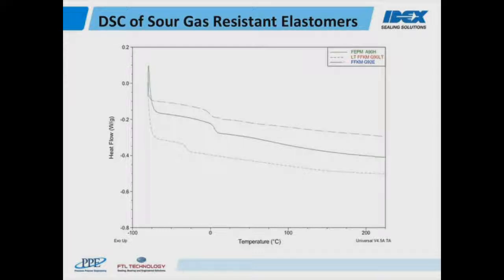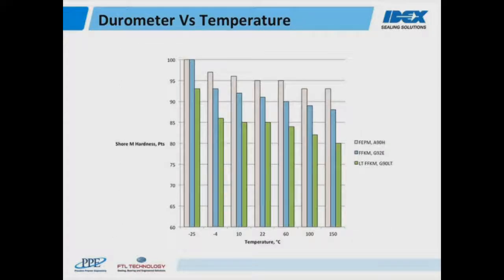To demonstrate this concept in a more tangible way, we can observe a durometer measurement on the materials at low temperatures. Here on this graph, the FEPM is the red bar, the FFKM is the blue, and the low temperature FFKM is the green bar. As you might expect, as the temperature decreases, the durometer will increase. Comparing to the glass transition we saw on the previous slide, the low temperature FFKM will still indent with the durometer at minus 25 degrees C, which is just above its glass transition, while the other 2 materials will not indent with the durometer, and therefore give a maximum reading.